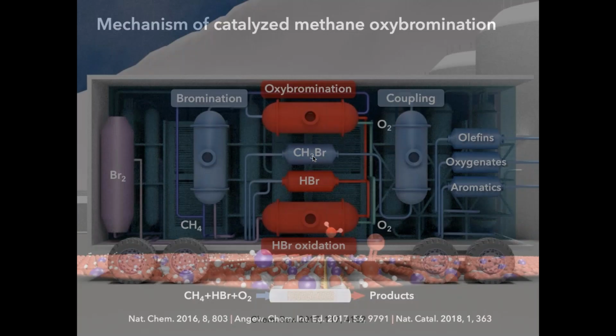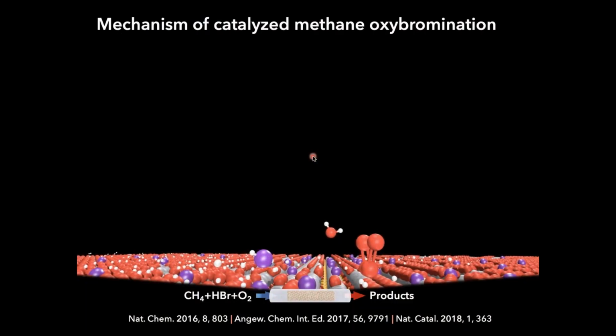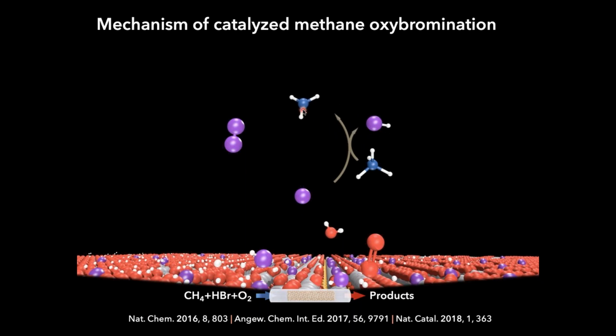So I'm going to show you an example of a cartoon of the mechanism of a catalyzed methane oxybromination. What the surface does is activate oxygen and HBr, and that will lead to water, molecular bromine and bromine radicals. And bromine radicals will react with methane in the gas phase to produce the methyl radical and HBr, and the methyl radical will react with bromine to produce methyl bromide. So this is a hetero-homo reaction, where the surface is making the bromine radicals or molecular bromine, and the attack of bromine radicals on the methane is happening in the gas phase.